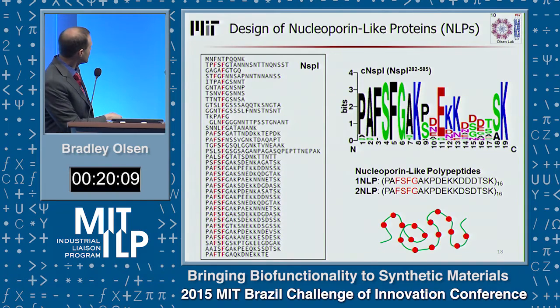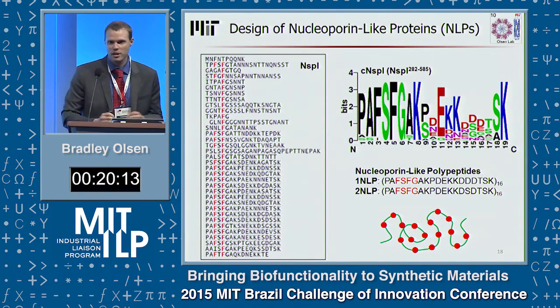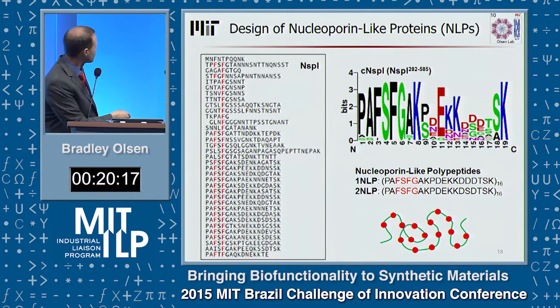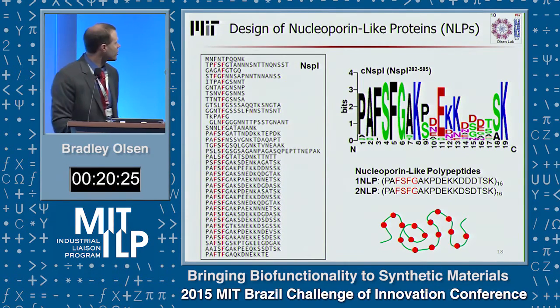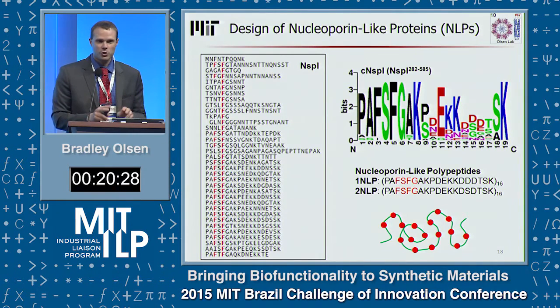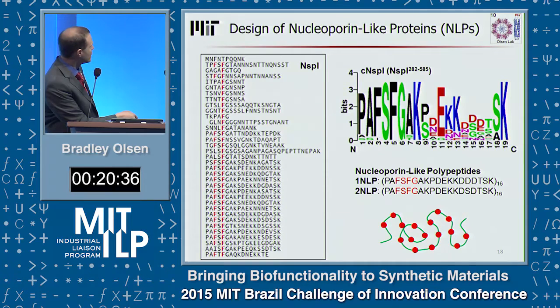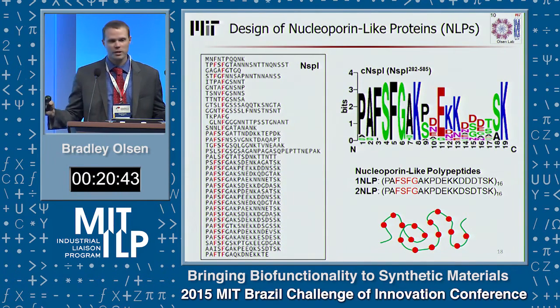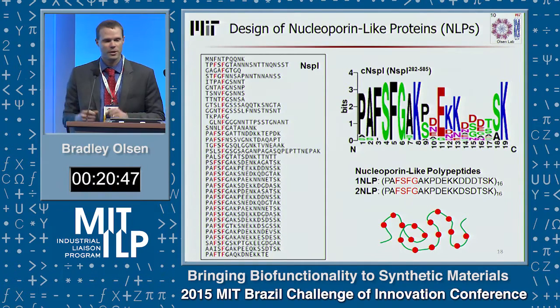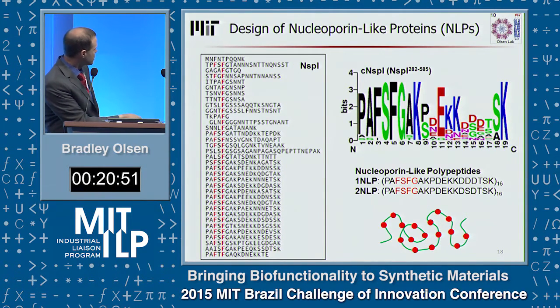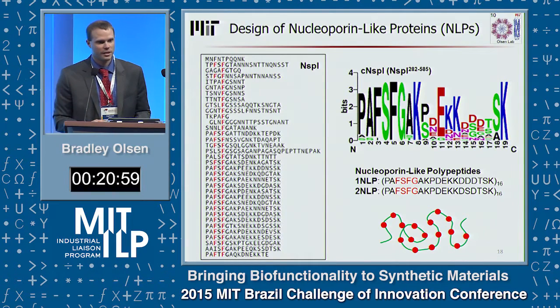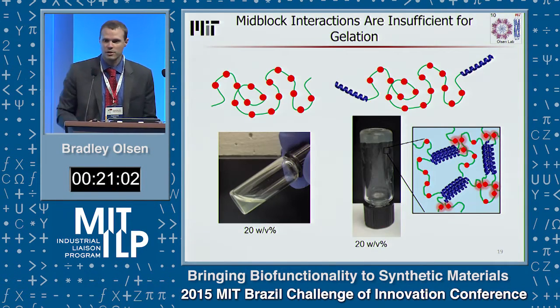We look at this C-terminal end, which is believed in biology to be responsible for the high selectivity of the protein. And so we did bioinformatic analysis on the C-terminal end, and we plotted a frequency map of the occurrence of all of the amino acids in this material. And what you can do then is, from this, extract two equally likely sequences that are the consensus for the functional unit of this protein. And so we did that, and we named them 1 NLP and 2 NLP for nucleoporin-like protein. And what we can do then is clone them into a full-length molecule just by repeating this same minimal unit of amino acids. If you do that, you get something schematically that looks like this, where these red dots are meant to represent this FG domain, which is believed to be a biological binding domain contained within this functional unit. All right, so we make this material and we express it recombinantly.